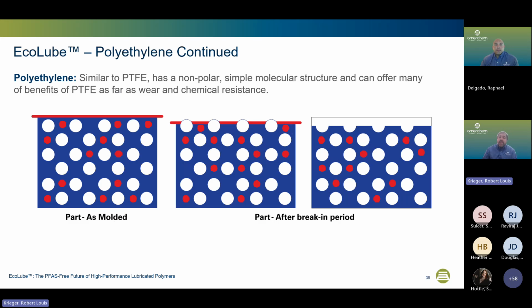So some types of this polyethylene, the ultra-high molecular weight polyethylene in particular, are designed not to melt in our process or your process during processing, but retain the small spherical particles that PTFE does. This allows for superior wear resistance after break-in, and it synergizes very well with silicone species. And it emulates the same sort of break-in and coating effect that Raf described before with the PTFE, where you have your silicone. When you first mold, the part wears away a bit, exposing the polyethylene particles in the surface. And then as it wears further, you get a nice coating of polyethylene both on the plastic part itself and the co-rotating surface over time. So you get that short-term wear and the long-term wear. Now, not every type of polyethylene can do this. So, we have different designations that do different things.